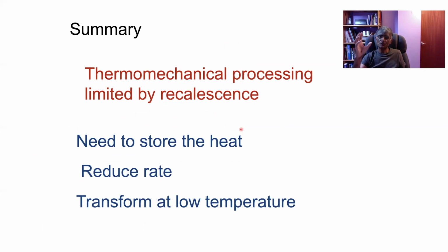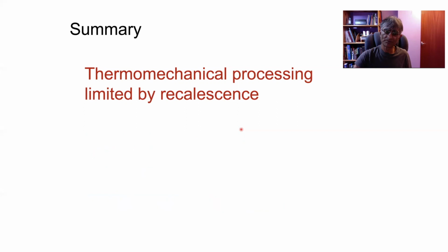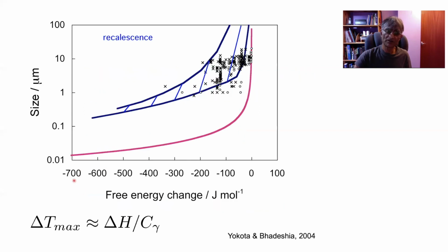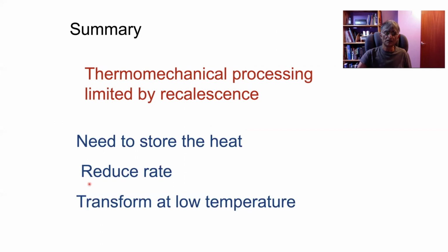And think about it, when we were talking about displacive transformations, the amount of stored energy due to the shape deformation in the case of martensite was 700 joules per mole, which is very large. If I go back to the previous slide here, you can see that's a large amount of energy you would consume in creating the elastic strains around martensite. Okay, we could also reduce the rate of transformation to allow any enthalpy to dissipate.